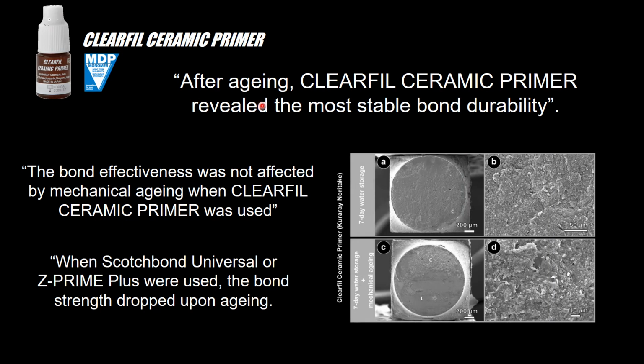So their conclusion: after aging, the Clearfil Ceramic Primer revealed the most stable bond durability. The bond effectiveness was not affected by the mechanical aging when Clearfil Ceramic Primer was used. When Scotchbond Universal and the Z Prime Plus were used, the bond strength dropped upon aging. And once again, I just put in the image here of the failure modes. Failure modes are so important. Everybody looks at bond strength. Failure mode is more important even than bond strength. You have to have a good bond, but then look at where they failed.